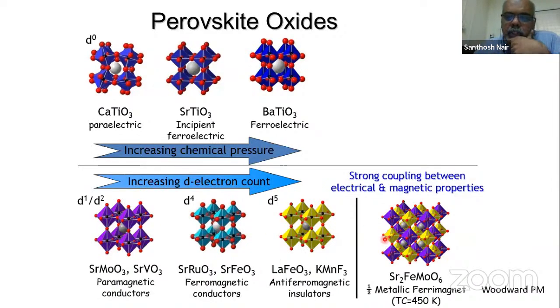And if you manage to put two different ions in the B site, instead of titanium, you put two different ions, iron and molybdenum, then you get this exotic system like a half-metal ferrimagnet. In this particular system, iron and molybdenum octahedra are shown in purple and oxygen in yellow, but they are ordered. Every iron ion has molybdenum as the neighbor. So depending on the extent of ordering, the properties can change.